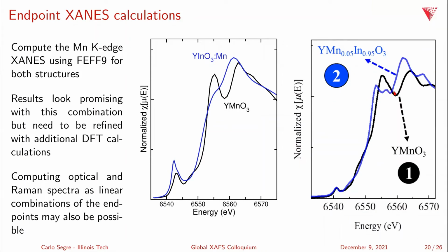Okay, and I was also wondering if in the DFT, did you have to start the manganese atom off-center to keep it from getting stuck in the middle? I have not had to, because there's enough asymmetry in the initial structure that it moves immediately off-center. And part of it is because I don't move the oxygen atoms. So the oxygen atoms are now much further out than they were for the YMnO3. So I just put the manganese in place of the indium naively, and it moved. It took a while, but it moved to this spot, which is pretty remarkable, actually.